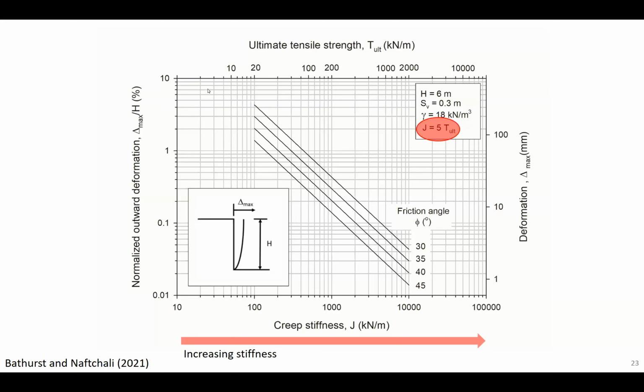The other thing that you can see on this plot is that the horizontal axis on the top of the plot is actually the ultimate strength, because a reasonable relationship between the secant stiffness and the tensile strength is a factor of 5. So this increases the utility of this chart. In case you don't have the creep stiffness value, you can estimate what it is using pooled data, where the stiffness is about 5 times the ultimate strength.